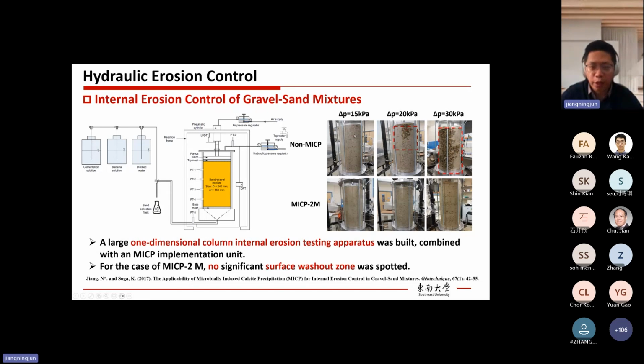So when the hydraulic pressure is not quite high, we can see only a little bit of erosion along the surface for the untreated samples. For MICP samples, no erosion at all. Then when the hydraulic pressure increases to 20 and 30 kPa, we can see very significant surface washout zones. So it means that the erosion happens a lot. But for MICP treated samples, still no erosion at all. So from the visual observation, we already see MICP works very well.